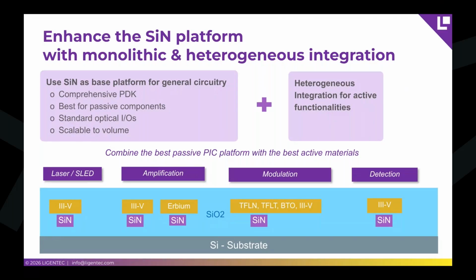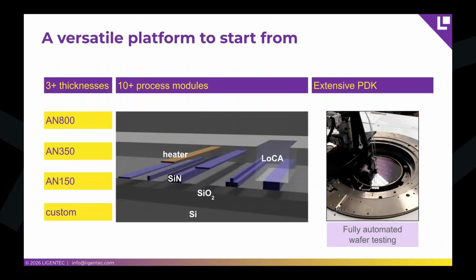So the low losses in silicon nitride passives, we have them in three different platforms. Why do we have three different thicknesses? These address different wavelength regions for different markets, and the process modules, you can stack different nitride layers, you can integrate heaters, you can integrate the local cladding opening, which is glass, to get access to the evanescent field of the waveguide, to have other materials interact, or in a biosensor molecules interact with your waveguide.